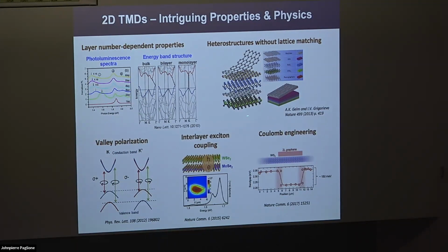If you compare these transition metal dichalcogenides to conventional semiconductors like gallium arsenide and so forth, they have very large exciton binding energies in their individual layers, but they also have a variety of band alignments, and you can create type 2 junctions and give rise to something called an interlayer exciton. It's an electron-hole pair that is bound between the layers and creates excitonic devices that you can modulate, for example, with strain. Also, because these are atomically thin layers, you have reduced screening effects, and you can modulate the electronic properties by simply changing the dielectric environment, right? So you can create PN junctions just by laying it on different surfaces that have a different electrostatic effect on the layer. It just changes the exciton and so forth.